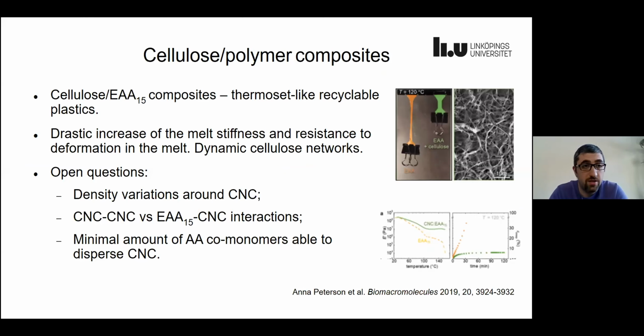And as I said, these composites, cellulose and polyethylene acrylic acids, are really interesting materials. They are thermoset-like plastics, which can be recyclable. So they are really interesting and relevant materials for today's economy. It is shown that by just introducing cellulose into these polymers, we can have a drastic increase of the melt stiffness and the resistance to deformation in the melt of these polymers. For example, here on the right, you can see a picture from the experiments where we have the neat polymer and the cellulose polymer matrix. And this is mainly, we think, because of the formation of dynamic cellulose networks, which can reform and adjust during heating and cooling.